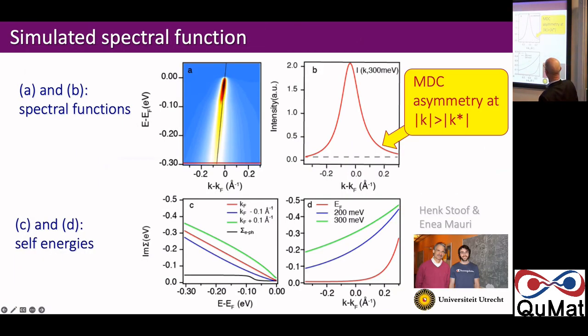So they generalize this to different temperatures. This is the spectral function rolling out of Inea's calculations and Henk's calculations. So that means they're in possession of the detailed physical self-energy from this ADS CFT semi-holographic model, and we're testing it with experiment. And if it survives that test, that means this is a very rich source of information. This can be used to calculate optics, can be used to calculate transport, any experiment you like.